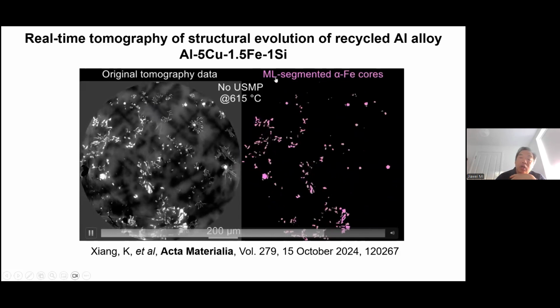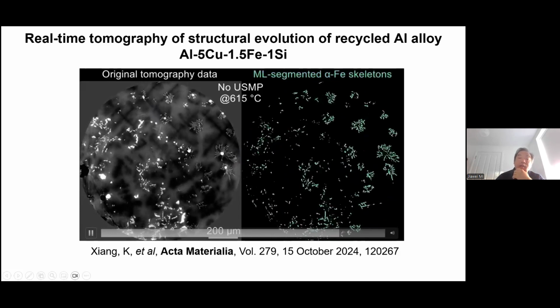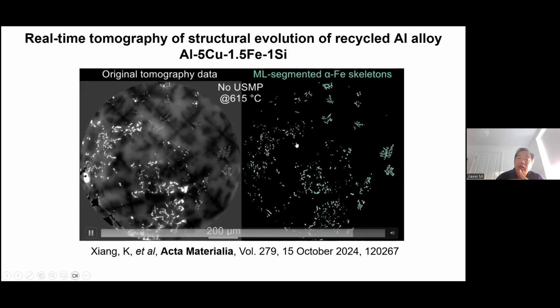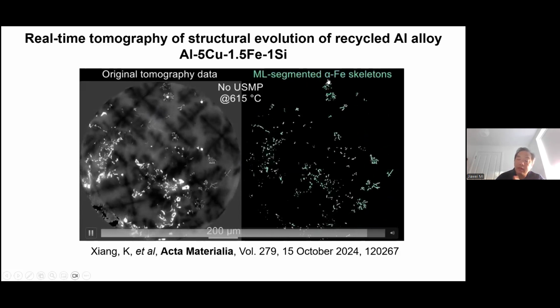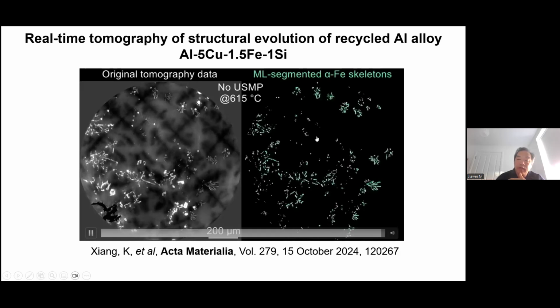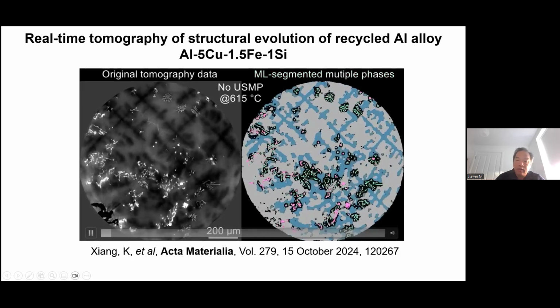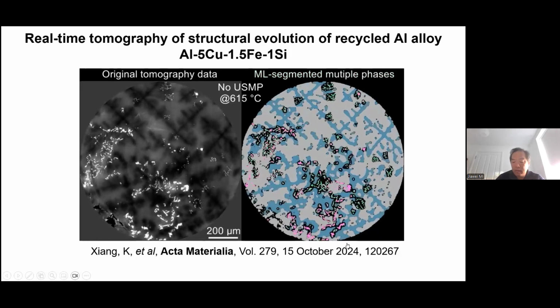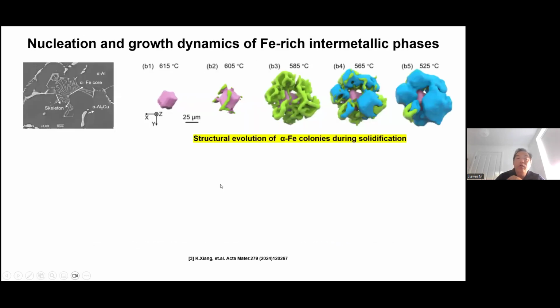So we're using a machine learning strategy to segment all the phases, and you can see we're quite successful, so we can even segment the different types of iron-containing phases through these slices. You can read the fully published paper here. And by using this, we can now isolate this nucleated core, how it forms at different temperatures, and how the shape changes from a globule to some kind of pyramid structure, and then